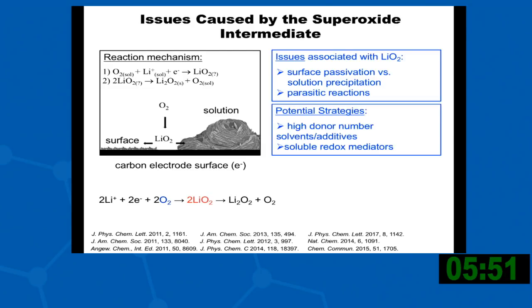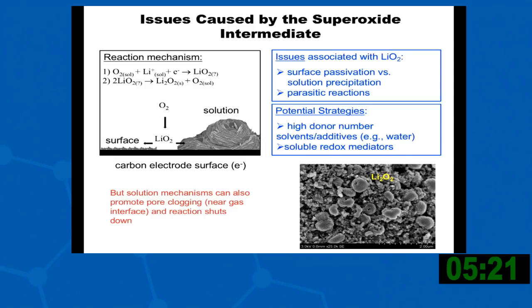And so the strategies that people are taking are to use very high donor number solvents that increase the solvation of the superoxides and the peroxides. And then you can transform this from being a surface reaction to a solution-based reaction, and you can form the beautiful large particles of lithium peroxide on the carbon structures that I'll show you in a minute. You can also use redox mediators to mitigate this reaction, and again, I'll show you that in the next slide. But the problem with the solution mechanisms is that you can get pore clogging because you form these massive particles which then block the transport of oxygen through the pores of your carbon electrodes